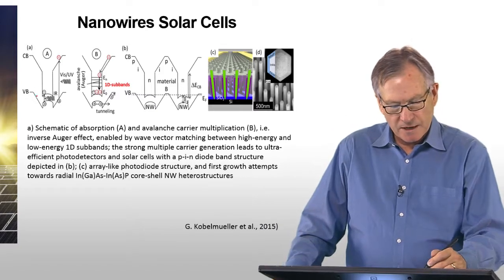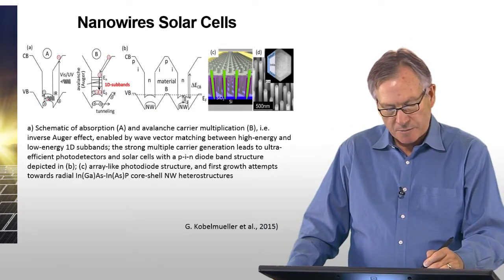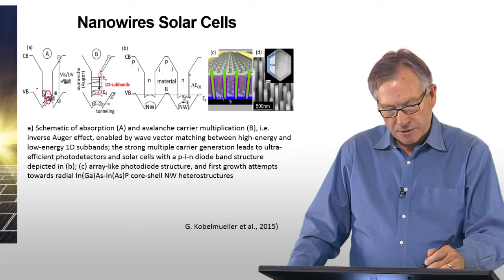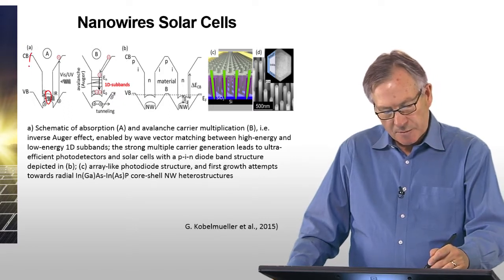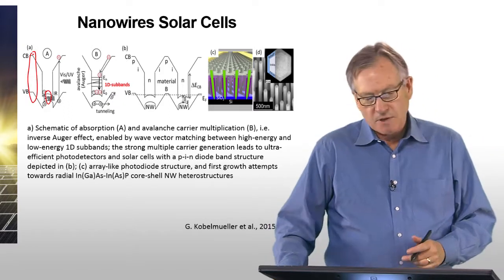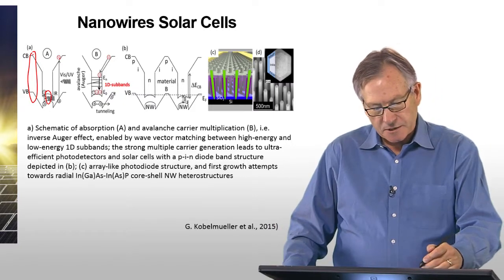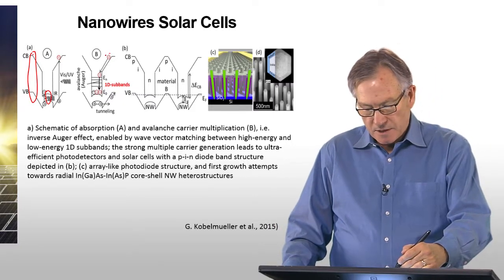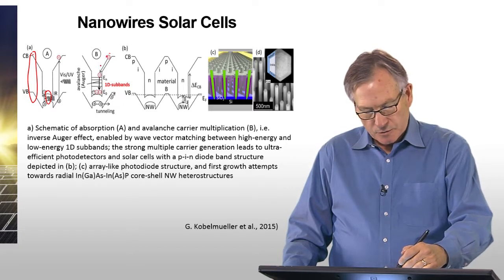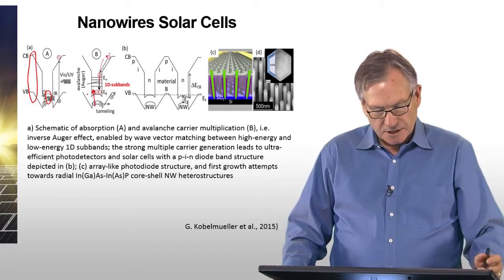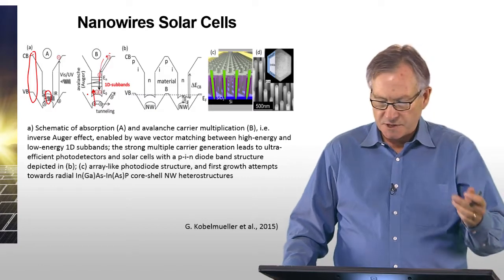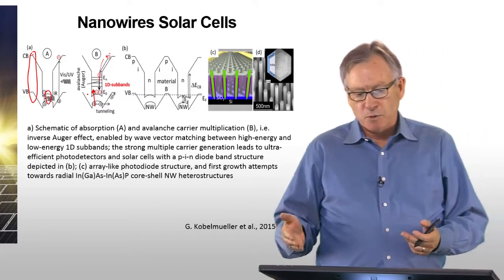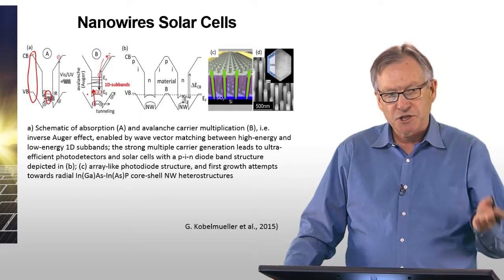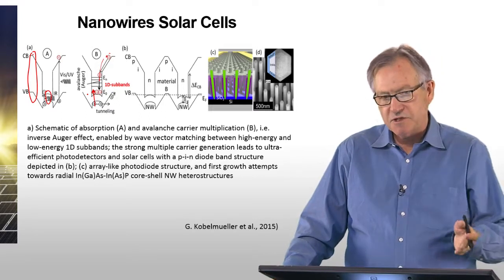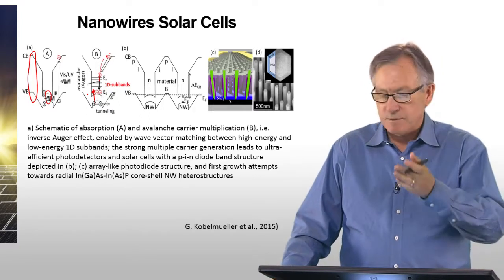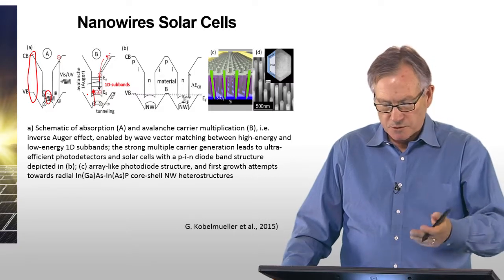So if you have a nanowire in which you have a narrow band gap material in the middle of the nanowire, and you have a wider band gap material forming the cladding layer, the electron-hole pairs that are excited in the cladding layer before they fall down can lose their energy and excite an electron-hole pair by the multi-exciton process. In fact, there's been experimental work recently that's shown that multi-exciton generation is quite strong in semiconductor nanowires, and therefore this is an approach that's of great interest.